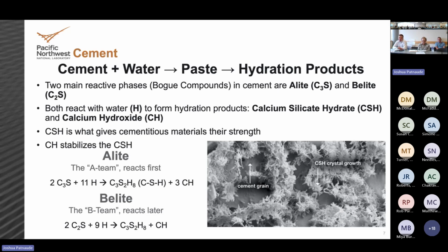So the two main reactive phases in cements are tricalcium silicate, which is alite, and dicalcium silicate, which is belite, C3S and C2S. Cement researchers like to have their own notation. They can't just use nice chemistry notation. So the notation at the end, that C3S and C2S, those are the cement notations for the specific compounds. So when you take cement and you react a cement powder with water, the alite, the tricalcium silicate, is what reacts first. So the calcium and silicon within that phase, that's what starts to dissolve when it interacts with the water, and you start to precipitate calcium silicate hydrates, CSH, and that's the primary contributor to the resulting cement structure.